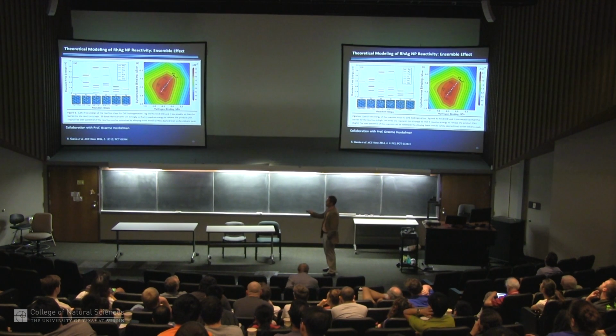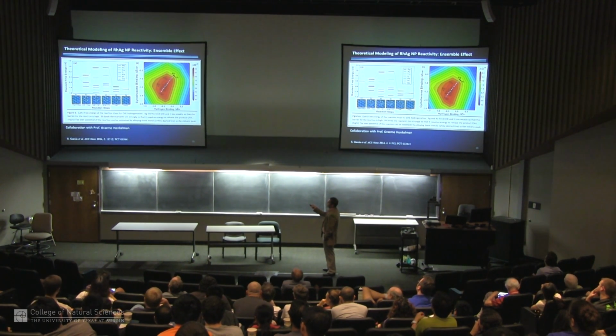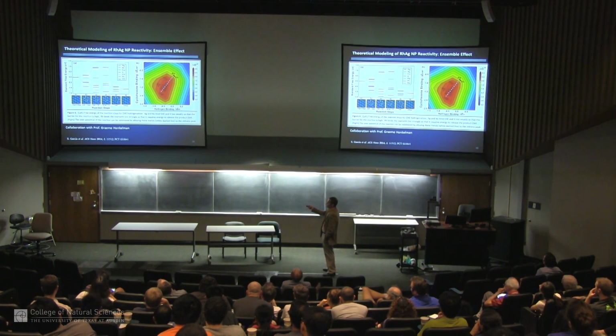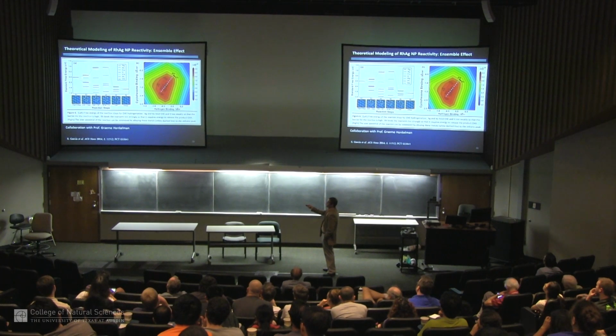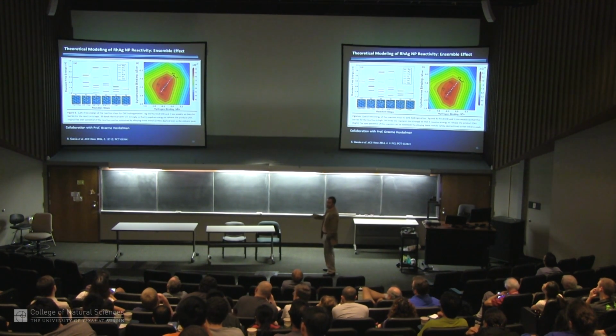And the good thing with this model is that we now don't assume one step in particular is rate limiting. Now they calculated for all of the FCC noble metals, and you can see rhodium in black has the strongest binding energy all the way down here, which is great, because it means you get everything stuck on the surface. However, now it's a problem because rhodium is very reactive, it can often chew things up. It now doesn't like to release the reagents, it doesn't like to do chemistry. Whereas silver, which is in red at the opposite end of the spectrum here, is useless at binding things. In fact, it can't spontaneously absorb these reagents, but it's very good at desorbing them.